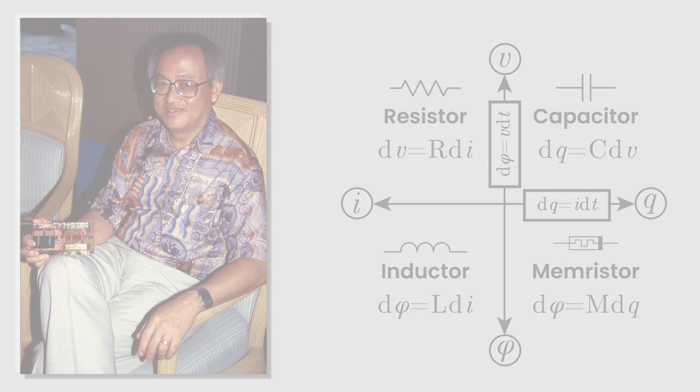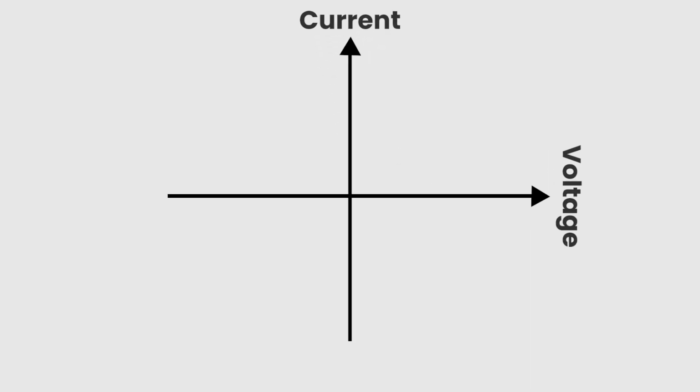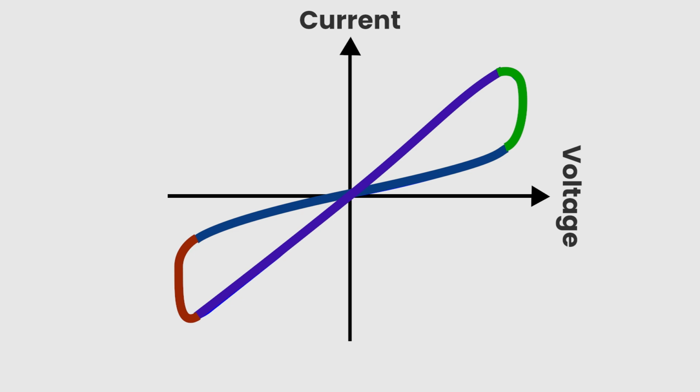The memristor's relation between voltage and current is a Lissajous function, with 2 states and 2 transitions. The 2 slopes which show conductivity are the low resistive state, LRS, and high resistive state, HRS. The transition from a low to a high resistance state is called reset, and the opposite is called a set. In this master thesis, we'll focus on Metal-Insulator-Metal Memristors.